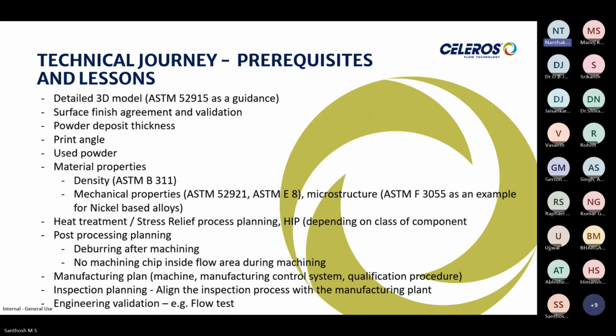The particular challenges we faced, one is on deburring. In this case, we used Inconel as a material, so deburring was a big challenge because Inconel is a very strong material. The burrs don't break or chip off easily like the other grades. So we found some innovative ways of doing this. We must also remember that in this particular case, we cannot do blasting. Even grit blasting cannot be done because the grit can get into the flow areas and block the flow. So we cannot do grit blasting, abrasive tumbling, none of these. We have to think about different options to deburr the part.